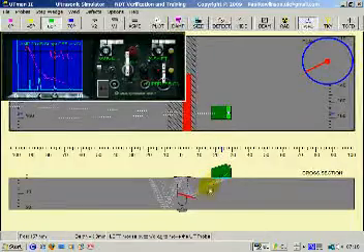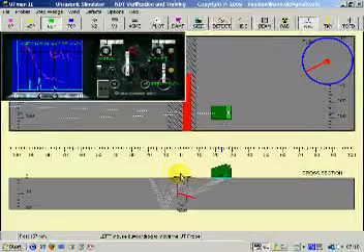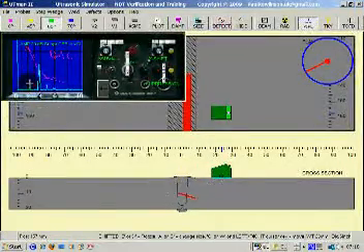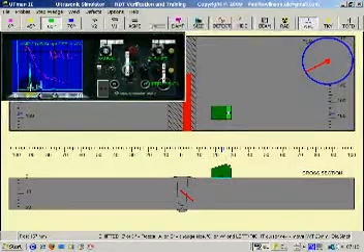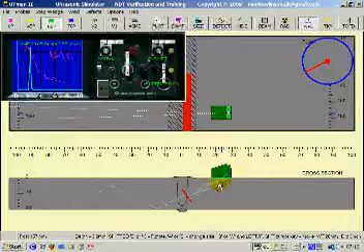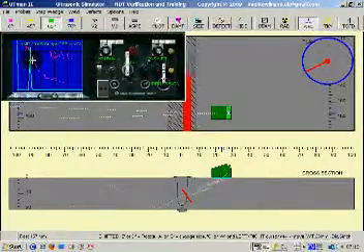As the sound hits the lack of fusion, mirror-like, and bounces up. The actual defect position is here, very low response. And again at 90 degrees to the lack of fusion, we get our best response here.